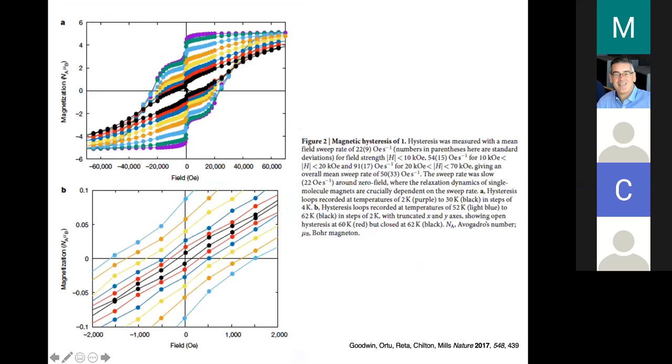So you see the effect in this plot where at zero applied field, you see this sudden loss of moment. In that terbium bisphthalocyanine complex, it would go all the way to zero. So you might have some open hysteresis here, but when you get to zero, all of a sudden it can tunnel. There's degeneracy of those plus and minus levels, and you tunnel and lose polarity.